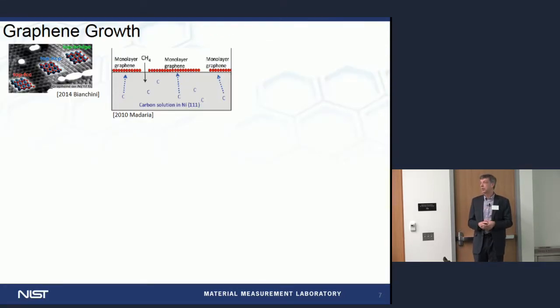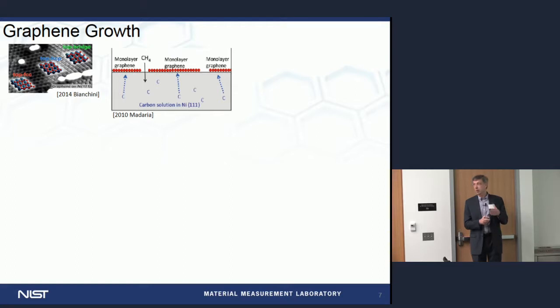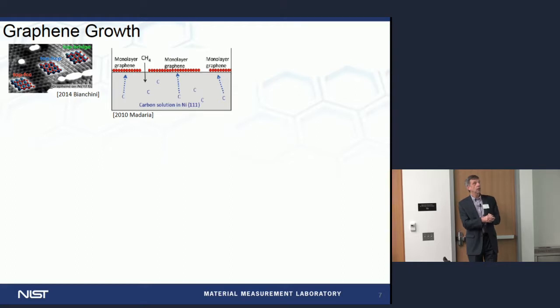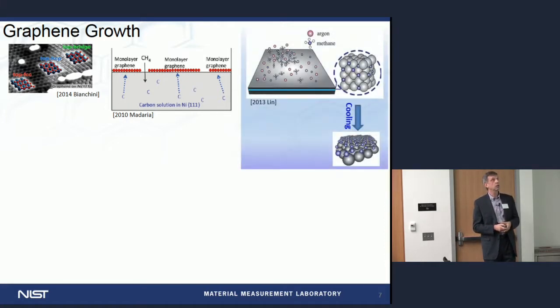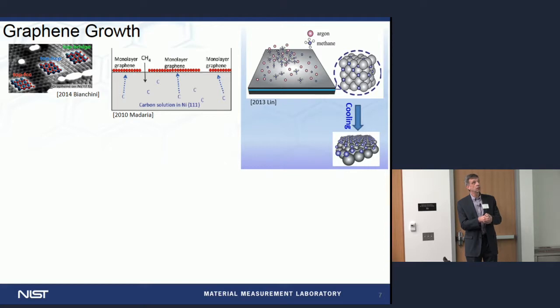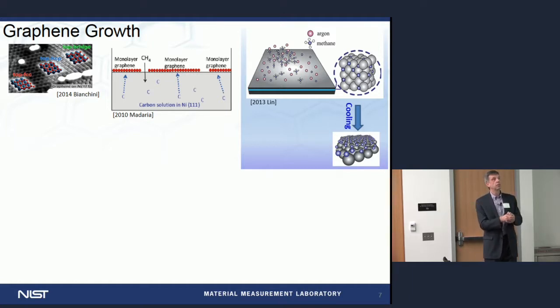Starting with graphene CVD on nickel: this is a familiar process. You purge methane or ethylene into the bulk of a nickel film or foil. Once you saturate the nickel with carbon, it precipitates back and forms a monolayer or multilayer depending on conditions. In a 3D view, the methane goes into the nickel substrate, carbon enters the lattice, and upon cooling of the wafer, carbon migrates and diffuses back to the surface, forming a single-crystal monolayer.